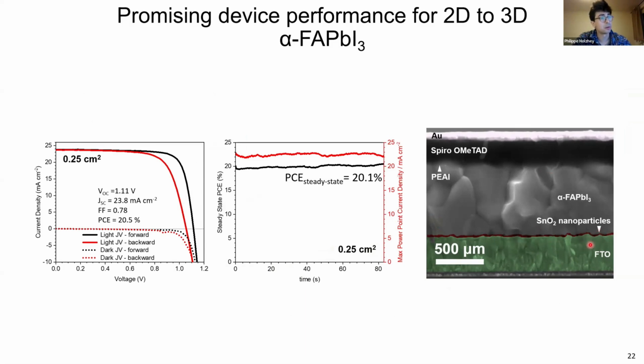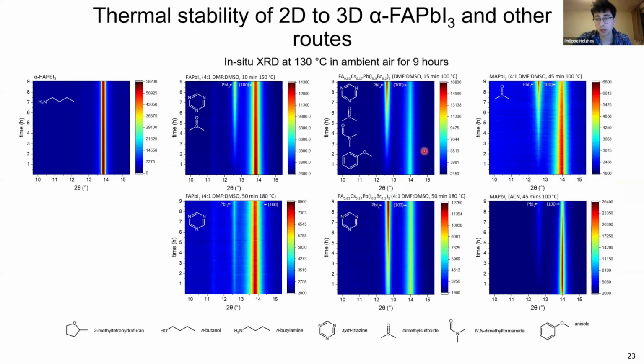This is FTO, then the tin oxide nanoparticles, then the FAPbI3, a surface passivation, and then a spiro and gold. And the really surprising thing about this study was really enhanced stability. So I measured this on a Rigaku SmartLab. It's a 2-dimensional XRD setup where I also have a heating stage. And this is measured in ambient air.